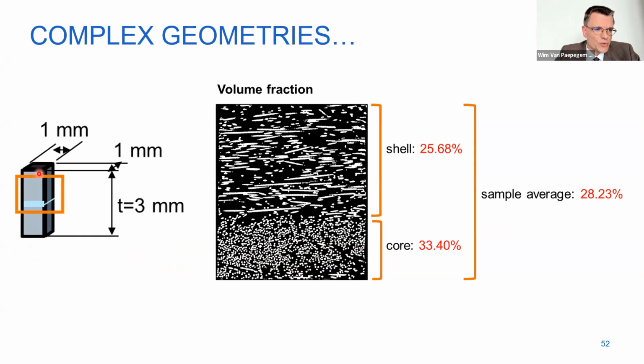Here you see a cross-section through the thickness. So this is the central part of the geometry, and here is the top. So we only see about half of it here. And then you see you have a quite aligned part on the top. And in the middle, the fibers are mostly under 90 degrees. So this has to do with the flow of the polymer and also the shear stress gradient in the flow. So this is called a core shell effect. And also even the volume fractions are not the same. So this already complicates a lot what we have shown in unidirectional arrangement.